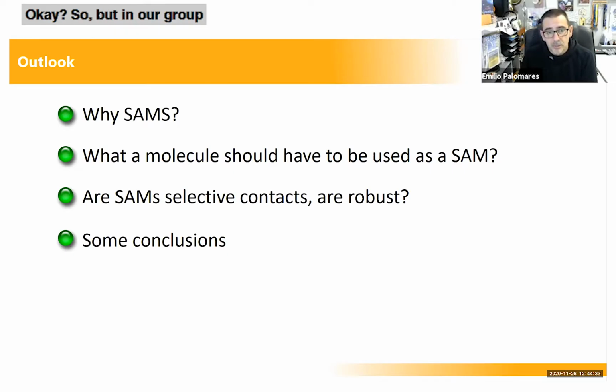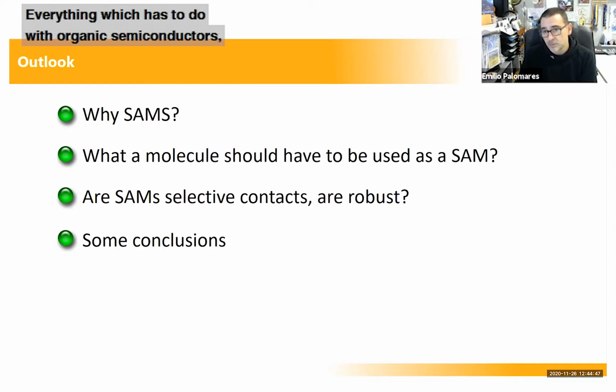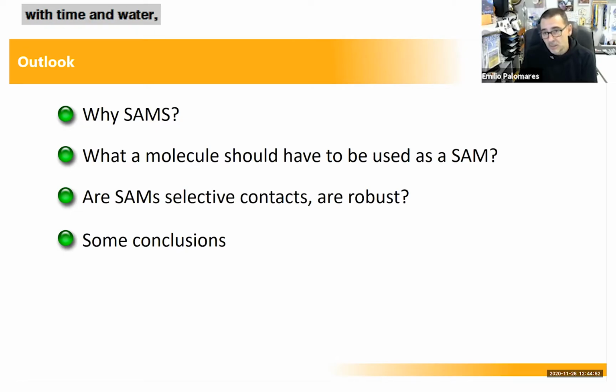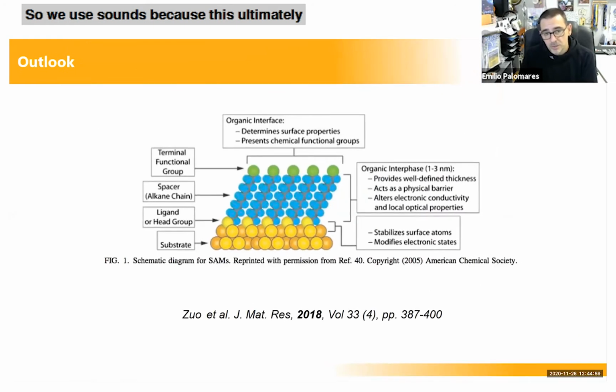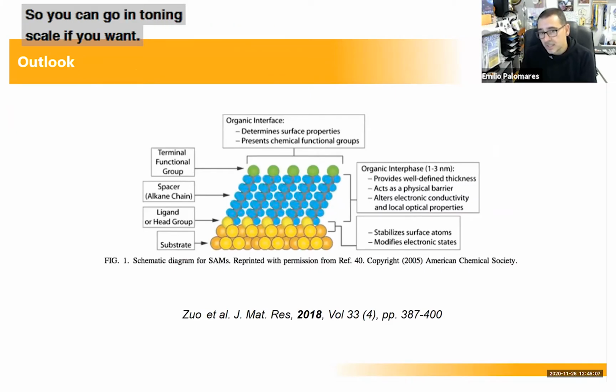But in our group, we're trying to replace one of the materials used in perovskite solar cells that makes the device unstable, which is spiro-OMeTAD, an organic semiconductor. Everything which has to do with organic semiconductors, either polymers or small molecules, with time and water, they become oxidized, and that compromises the stability of the solar cells. So we use SAMs because there's a lot of literature on self-assembled monolayers, and they are easy to synthesize, so you can go to tonne scale if you want.